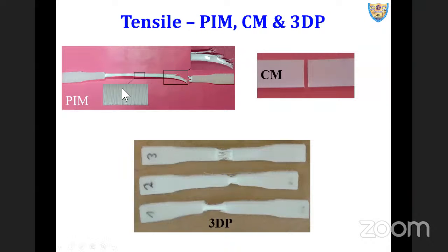Then we compared the same high density polyethylene prepared using injection molding, compression molding, and 3D printing. It is the same grade of high density polyethylene. Now, if you see the tensile, when we apply a tensile load, the behavior is ductile in injection molding, brittle in compression molding, and a combination of these in 3D printing. By looking at these failure features, you can immediately figure out that 3D printed HDP will definitely have done better as far as the tensile moduli is concerned. No doubt straining is low, but the load carrying capacity might be really good, and even the modulus will be really good.